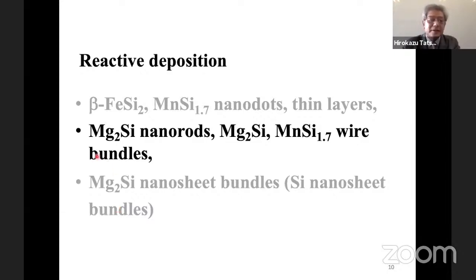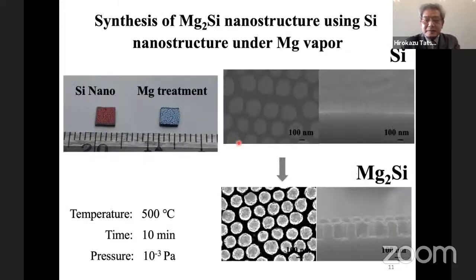So I would like to introduce the formation of magnesium silicide nanorods and wire bundles. This structure can be applied to photonic crystals. For silicide, it's not easy to make such structures by a top-down or bottom-up technique. But silicon is an easy material to make such structures. First, we make this structure in silicon, and then after magnesium deposition, these rods become magnesium silicide.